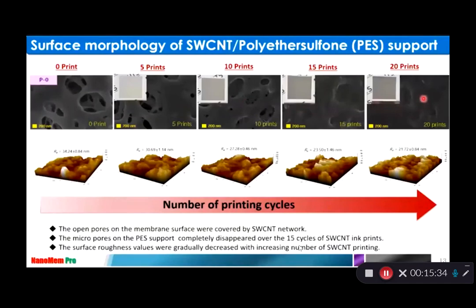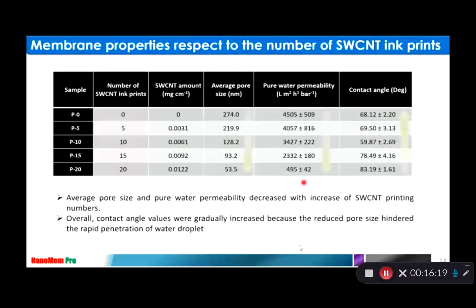You can see that all the CNTs blocked their pore size, and overall their roughness is reduced from 34 nanometer to 21 nanometer, and you can see how the color of the membrane changes. When you see the 5 times and 20 times, the black color also changed on the surface of the membrane. So this is the membrane property with respect to the number of the SWCNT ink prints.